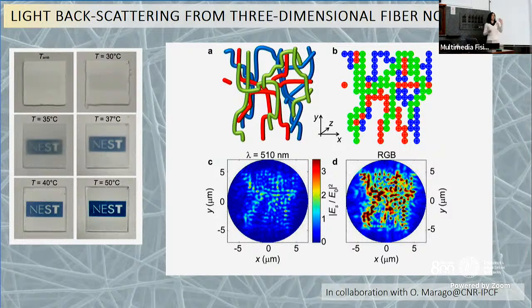Basically, the web of nanofibers has a very high backscattering ratio, so a lot of light is backscattered from the fibers. This is not the same for the film. So these are nanofibers, but when you increase the temperature, they become like a film, and so the film becomes totally transparent, okay?